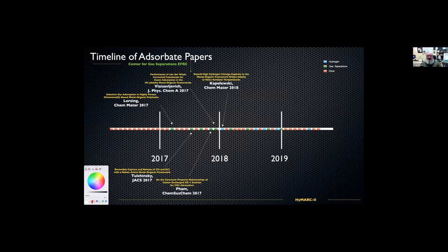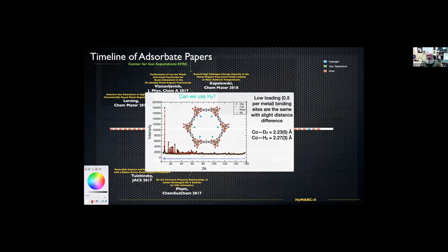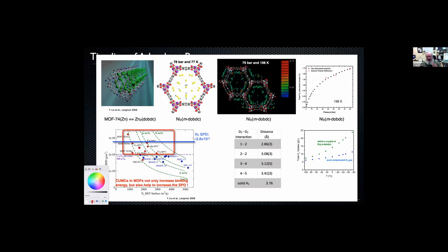I'm not going to talk about hydrogen quasi-elastic scattering or INS anymore, but just to summarize all that hydrogen work, hydrogen absorbed in these metal organic frameworks results in hydrogen interatomic distances that are much more compressed, even compared to solid hydrogen at 20 Kelvin or below. And so it's 77 Kelvin, 78 bar. This is super dense hydrogen.